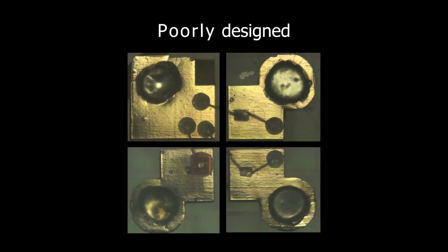Remember this image from earlier? We used this example to talk about delamination. Delamination led to the failure, but was not the root cause. The manufacturer of this LED chose ENIG as the electrode plating. This was a bad choice. The LED adhesive was unable to adhere to the gold surface. Silver plating is more commonly used and is a better choice for electrode plating.